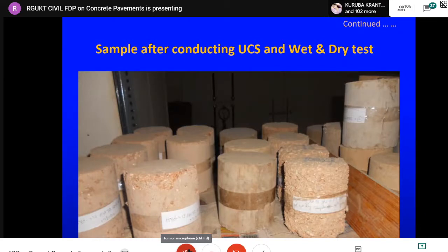Mainly this test is conducted to check the durability of the cementitious materials. Durability is one of the major issues when you are using cementitious materials for stabilizing, because you are using a very low quantity of cement. In the case of PQC, as we discussed this morning, if you go for M40 grade concrete, you use approximately more than 400 kg of cement. Whereas in these cases, with 2% cement, approximately 50 or 60 kg of cement per cubic meter is used. So in those cases, there is definitely a possibility of durability issues over a period of time. To check that, you have to conduct the wet and dry test. We have to dip into water, and there is a standard IS specification for the wet and dry test also. It is a total 24 days test.